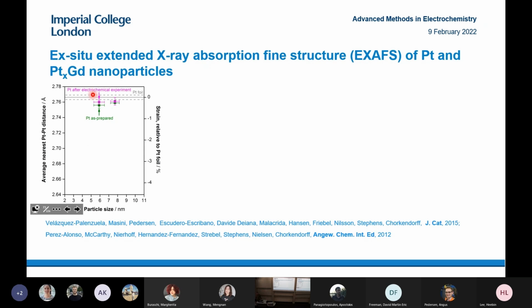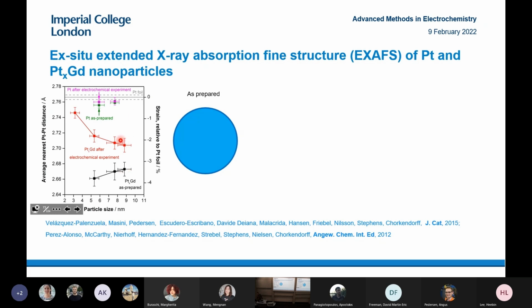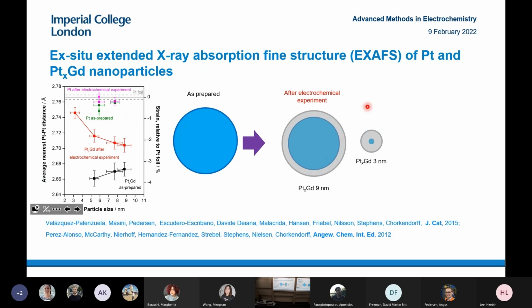So here are the platinum nanoparticles, both before and after electrochemistry. We see that there's no difference in the platinum distance. Now here's platinum gadolinium as prepared, as a function of particle size. And now we're going to show what happens after electrochemistry experiments. What we see is that for the smallest nanoparticles, the platinum distance is quite similar to bulk platinum, but for larger nanoparticles, we see more compression. What we think is happening is that for the smaller nanoparticles, you're leaching out almost all the rare earth, which is consistent with the TEM images where we don't see much rare earth left, but for the larger nanoparticles, we still have a lot of rare earth left in the core.